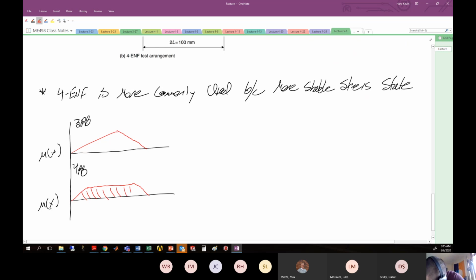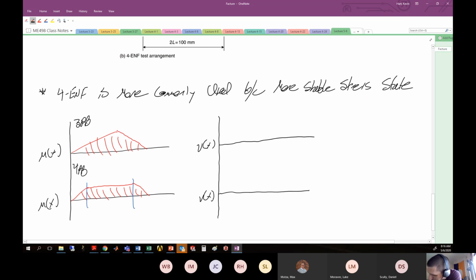All right. So what I mean by it's more stable is that if you're trying to propagate a crack in 4-point bend, if you have a stress state that is constant inside of this region, it's much easier to handle. As opposed to, let's say my crack is here and then it's moving a little bit. Now it's here, moving a little bit. Now it's here. Well, I'm changing the stress state at those particular locations. All right, not so great. And since we're a little more concerned about shear, the shear diagrams are also telling. So remember your shear diagram, V of x, for 3-point and 4-point bend. For 3-point bend, you have something that looks like this. And for 4-point bend, you have something that looks like this.